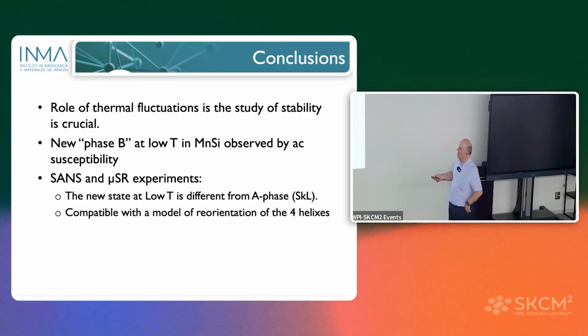And what we observed, we call phase B. SANS and muons are telling us that our data are compatible with a rotation of the helices at low temperature. And then I can tell you even more information. We collected muon data in the skyrmion lattice and in the so-called A phase. And this data can be fitted easily with a model considering four helices. We don't need to form skyrmions.